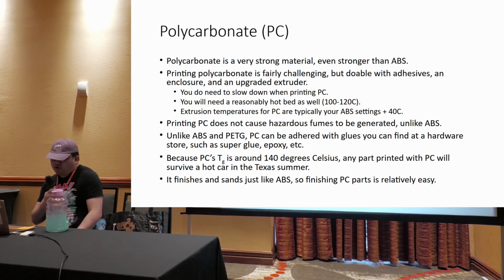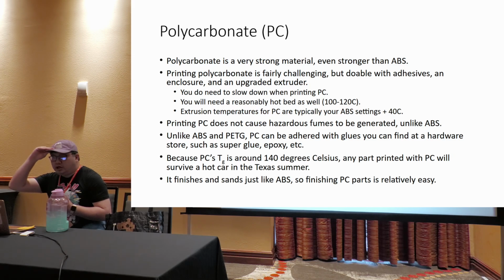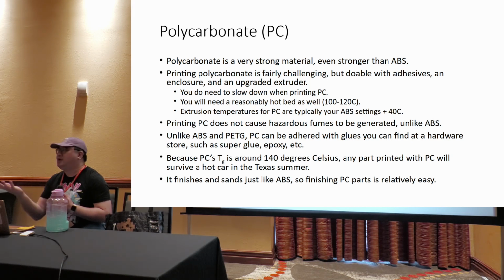And a lot of folks avoid printing polycarbonate because it is fairly difficult, but with the adhesives that have come out, and also with improved enclosures, you can actually print polycarbonate fairly easily as long as you do a few basic things. You basically have to slow down, maybe half the speed of PLA prints. You will need a fairly hot bed, and then your extruder temperatures will probably be ABS settings plus 40 degrees Celsius, and that will usually get you decent printed polycarbonate.